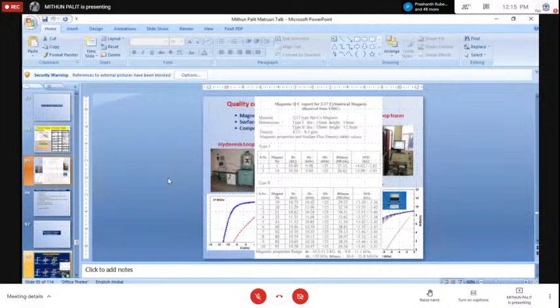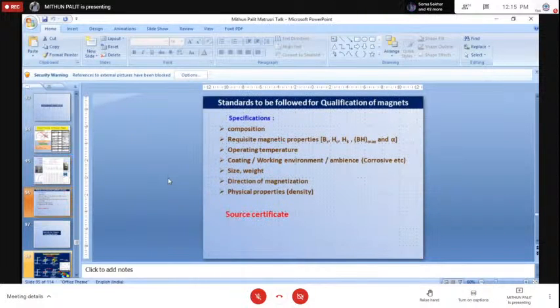After that, we have to do a lot of measurement: we do the BH loop measurement and also its intrinsic loop, and also measure the magnet. Once you make a particular shape, you cannot put it under the BH loop tracer. So how will you characterize it? There we use a probe known as the Hall probe, which is cylindrical type. You touch that probe on the surface of a machined magnet, and you will know what field it gives at a particular distance from the surface.